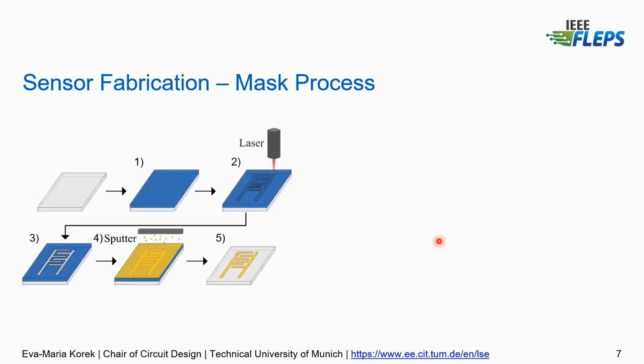So we tried another fabrication process, which is a mask process. And it's really simple. You can use any kind of substrate. Here in this case, we used a PEN foil. We covered it with wafer tape that is used in every CMOS process. And then we used a laser to structure the electrodes. And we removed only the inner part for the electrodes and sputtered 100 nanometer gold on top.